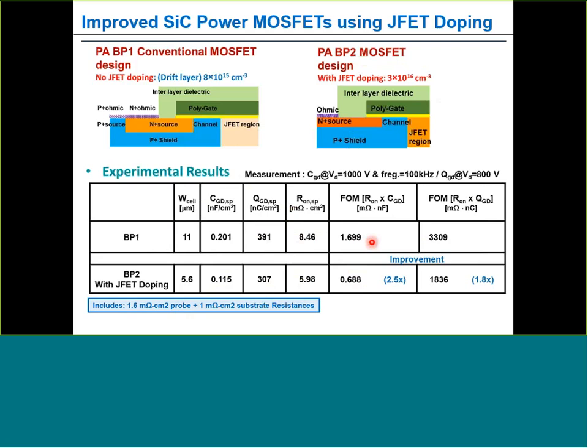The numbers for BP1 are probably similar to Gen 1 MOSFETs that were being sold by the industry. The numbers here are closer to the Gen 2 MOSFETs without subtracting these contributions. If you subtract the probe resistance then our numbers turn out to be a little bit better than what we see in our Gen 2 devices. So once again, this technology is available for licensing if it's of interest to you.